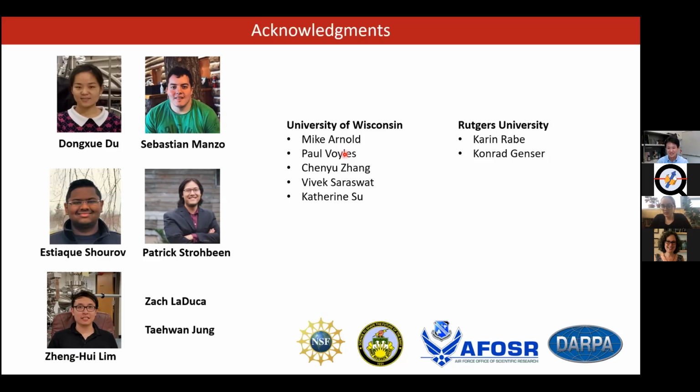Okay. And do you have any guesses if it has to be graphene or other van der Waals materials might work as well? Yeah, so I think you can think of it from several perspectives. One perspective is to think about the lattice potential of your 2D template material. And from that perspective, graphene might be a nice choice because it's all carbon in the basis. So minimal fluctuations of the graphene's lattice itself. An alternative you can think about might be hBN, but because it's a material with a 2-atom basis, there's some fluctuation between boron and nitrogen sites, and maybe that might interfere with the substrate potential itself. And I think Jiwon's group has done some with hBN, and they've had some limited success growing on top of hBN. But it's certainly not been as exploited as the graphene case.